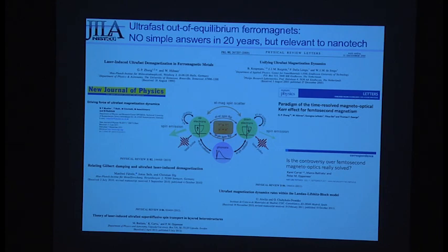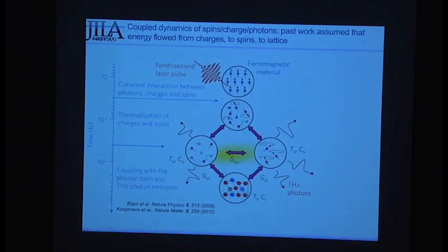You have hot electron generation, electron thermalization, electron-electron spin flip, electron-magnon spin scattering. There's also superdiffusive spin transport. So there's a whole lot of mechanisms. You can arrange them in a sort of order as a function of time: the very fast initial reactions, then the hot electron cooling, the spin flips due to collisions with phonons, and eventually the lattice heats. But it's a strongly coupled system with many interactions happening at the same time. So there is no first principle description.